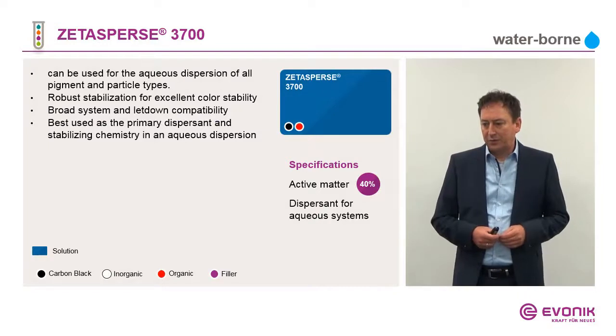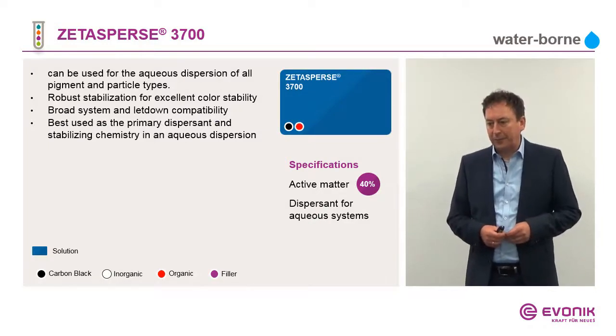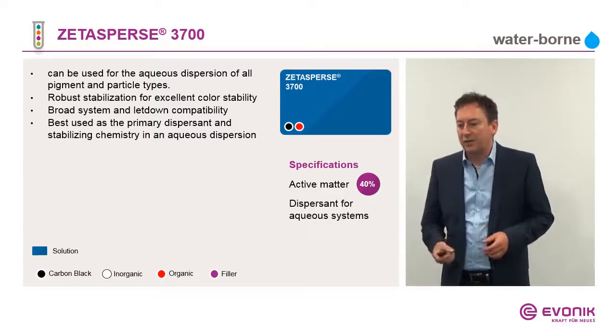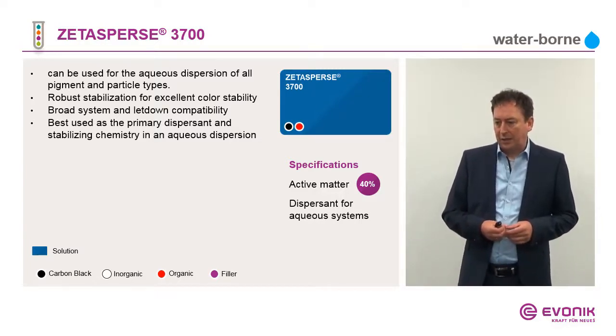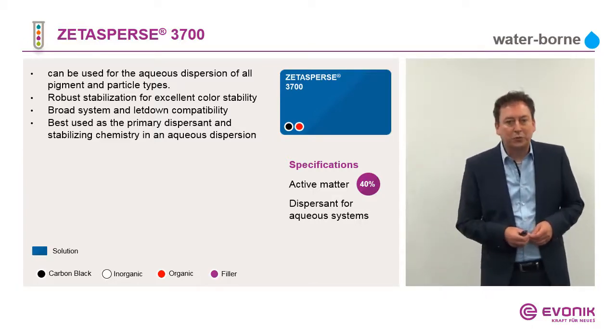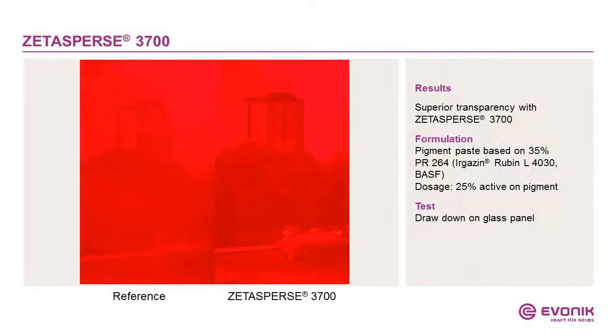The 3700 high polymeric additive gives very good stabilization, is very compatible, and it is very good with DPP pigments that you can see here. The results with DPP with the transparency. So transparency is very important in automotive coatings, and the 3700 gives very good transparency here with very critical DPP rubine with the PR264. All the customers have problems with this, and the 3700 can stabilize. This pigment gives very good transparency.